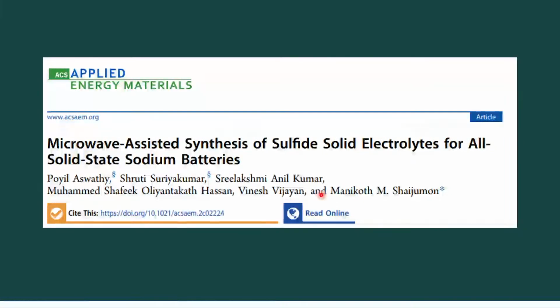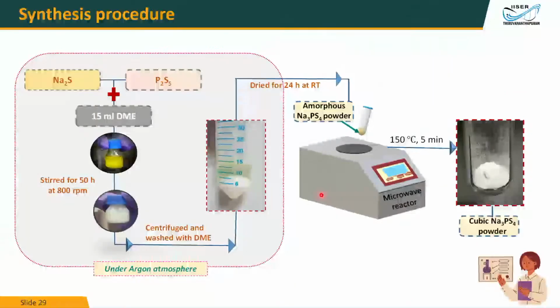Nothing worked. So when we were completely dejected and about to give up this project, we came up with this microwave reactor. Do we have one in our college now? Yes. It is a boon to all of you, especially those working in chemistry synthesis. You can do simple synthesis like hydrothermal, solvothermal, all of that very quickly. It has a microwave vial as a container, and we felt that it was airtight also. So rather than trying to seal it ourselves, we took this microwave vial inside the glove box, added our precursors into it, took it out after sealing and then heated it, and for the first time we were able to get cubic Na3PS4 by microwave heating.